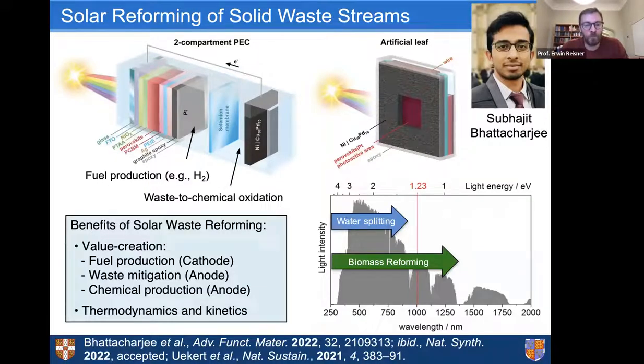Okay, so what about now replacing the water oxidation by waste to chemical oxidation? This is work here by Subhajit. What we did here, we used again the same perovskite stack as before on the photocathodic side. The only thing is we reduced the CO2 reduction catalyst to just platinum to keep it simple and just make hydrogen. And then instead of using a bismuth vanadate second light absorber, we do not need a second light absorber, for the reason I've mentioned before, because it's thermodynamically much easier. We only use the dark electrocatalyst for waste to chemical oxidation. In this case, we use nickel foam, where we co-deposited a copper palladium catalyst.